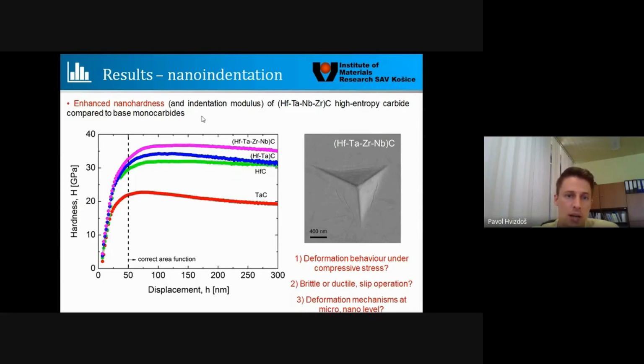So to prove that this is the case, we did basic nanoindentation, and we compared the results with monocarbides. As you can see, on the left side you can see only two monocarbides, tantalum and hafnium, but this is my fault because I forgot to insert the additional graphs we have. But believe me, hafnium carbide is the hardest of the four monocarbides, and tantalum carbide is the softest. So the other two, niobium and zirconium carbide, should lie between them. What is interesting is that even the binary hafnium tantalum carbide has higher hardness, but this four element high entropy carbide has even higher hardness, which fits the theory we thought of at the beginning about the lattice distortion.